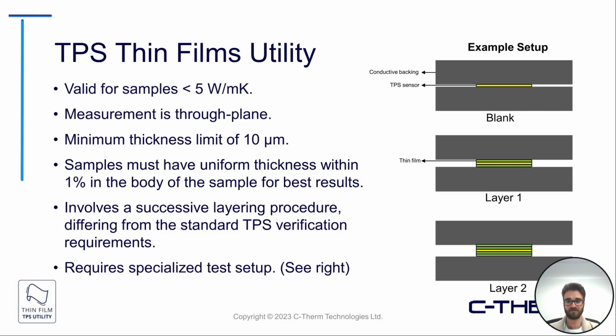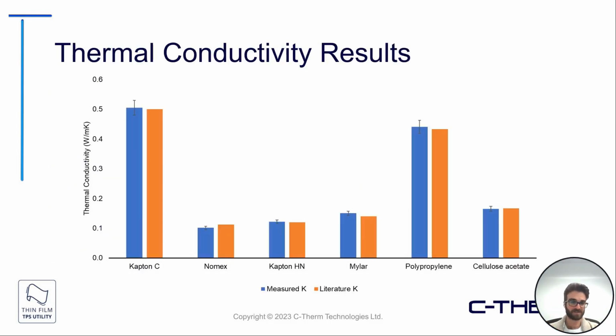You can see this setup involves an iterative measurement process where you take a blank measurement, so it's your sensor around a conductive backing material, and then you successively add in the layers of the thin film, taking measurements as you go. But this is ultimately a way to test really thin film materials. Here are some example conductivity results that were obtained on some standard or known, well understood materials. So the measured results compared to literature are in very good agreement there.